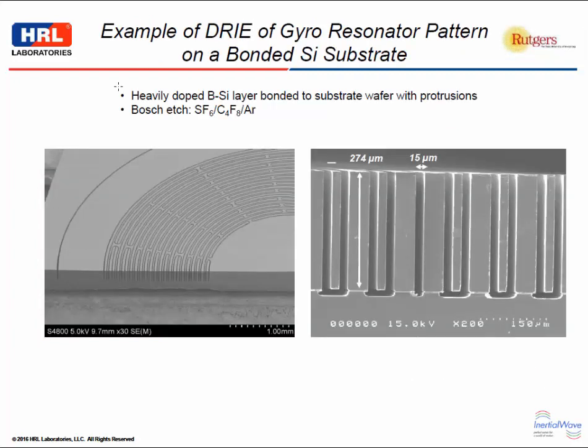So now we go to the silicon processing. This is a test wafer where we use this Bosch etch, an SF6 based etch, to etch the heavily doped boron silicon layer. You can see we're etching down about 275 microns, getting pretty good fidelity of the silicon etch. This would be the resonator section of the gyro, and these sections that are bonded are the inner electrodes for the silicon DRG that are energized by the outside circuit.